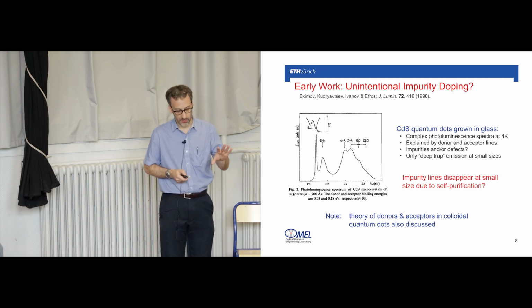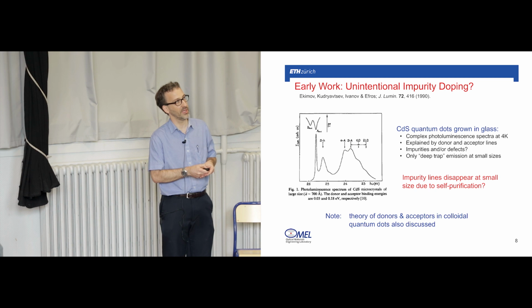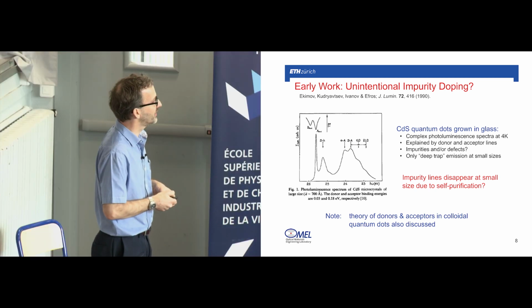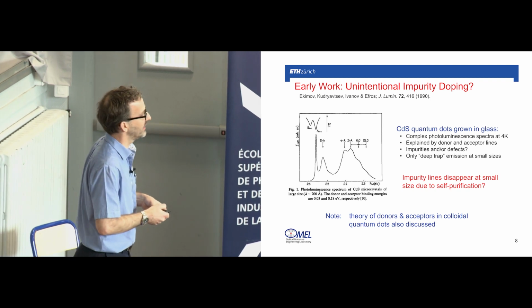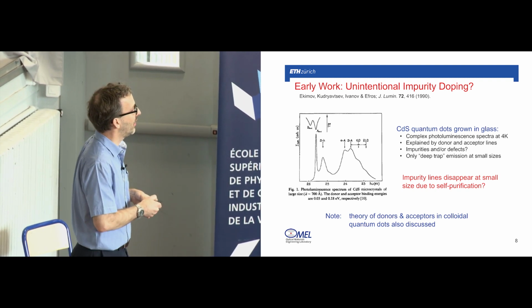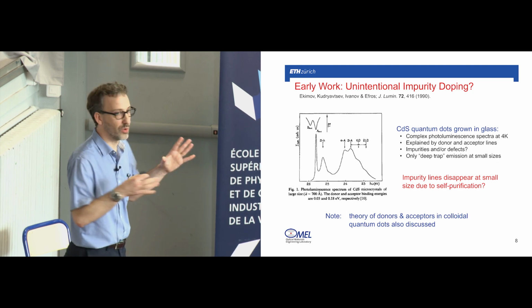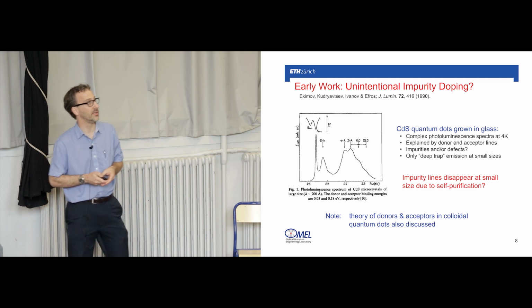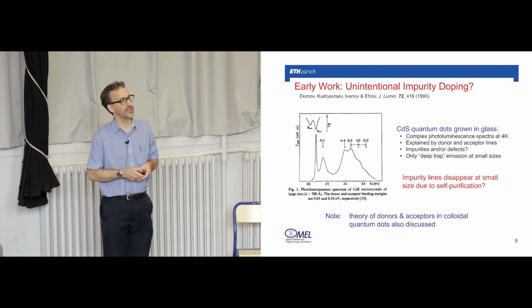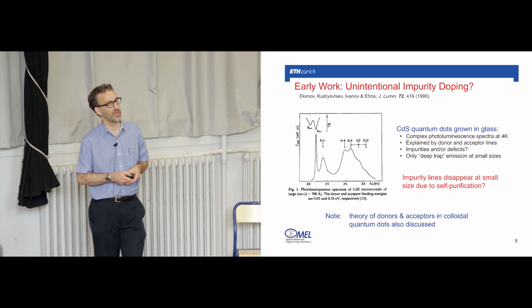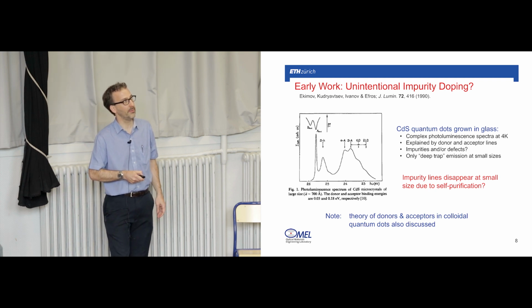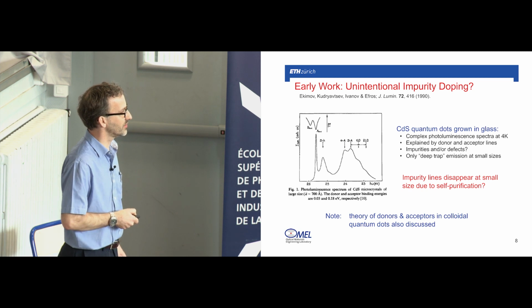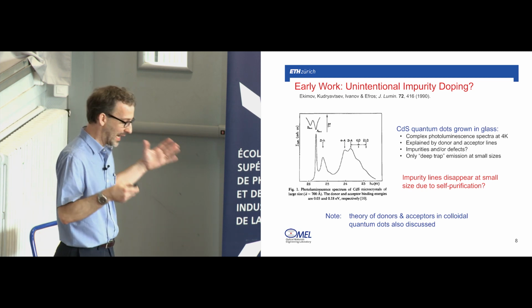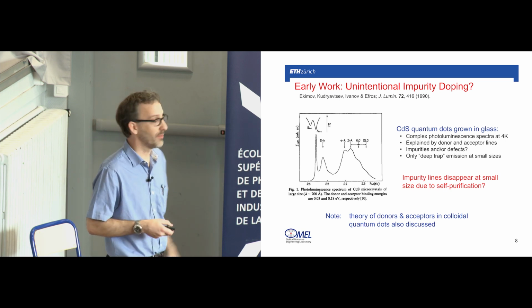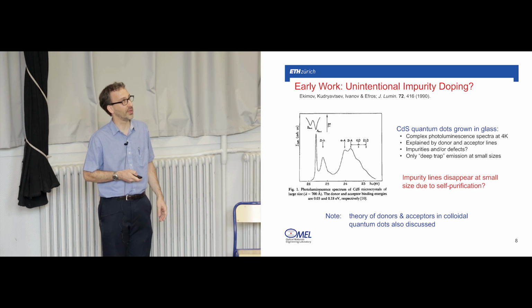Now, for the self-purification picture, this seemed to support self-purification, because the nanocrystals here are large, 700 angstroms in diameter, but as they went down to more typical nanocrystal sizes, all of the structure disappeared, and they only saw this, quote, deep trap emission that we often see at low temperature in nanocrystals. So this seemed to suggest that the lines that were maybe due to impurities were disappearing at small size due to self-purification. I also want to point out that in the same paper, Sasha worked out the theory of donors and acceptors in colloidal quantum dots, and how the donor or the acceptor changes its properties as a function of radial position, so there's a lot of useful things in this early paper.